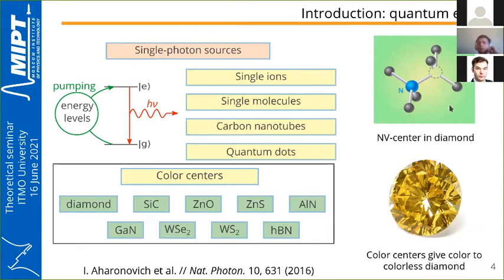The slide shows the most studied of them, the nitrogen vacancy color center in diamond, which comprises a nitrogen atom that replaces a carbon atom, and the vacancy, which is the absence of a carbon atom. Color centers give color to otherwise colorless diamond, because a defect-free diamond has no energy levels in its band gap, which is why it doesn't absorb optical emission. But color centers have energy levels in the band gap that absorb and emit light in the optical part of the spectrum.